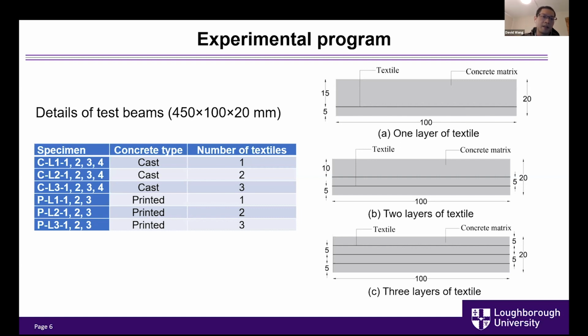The beams have a relatively small size, which is 450 millimeter in length, 100 millimeter in width, and 20 millimeter in thickness. The reason we choose such a thin section is that we are trying to apply the textile into thin-shell concrete members. And we use different numbers of textile layers in our samples. You can see from this figure, we have 1 layer, 2 layers, and 3 layers. Between each layer of the textile, the spacing is 5 millimeter. In addition to the number of textiles, we also compared the difference between the cast textile reinforced concrete and the printed textile reinforced concrete.